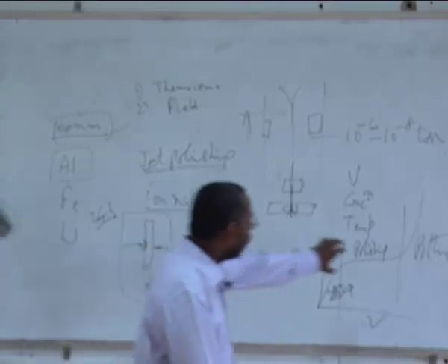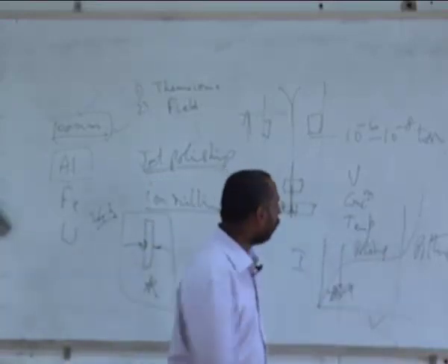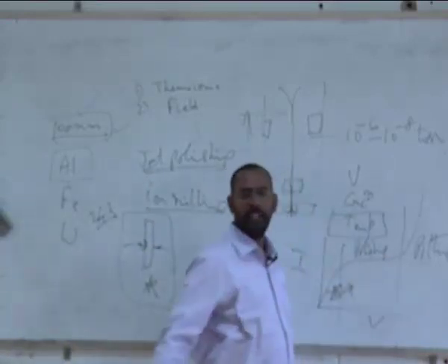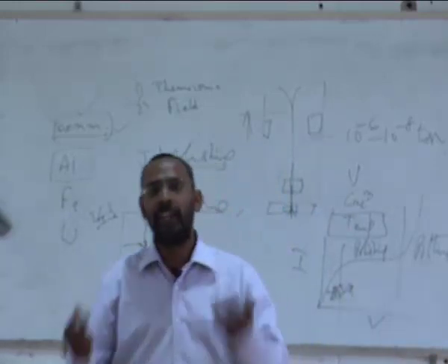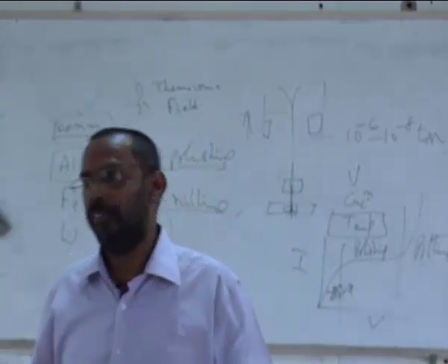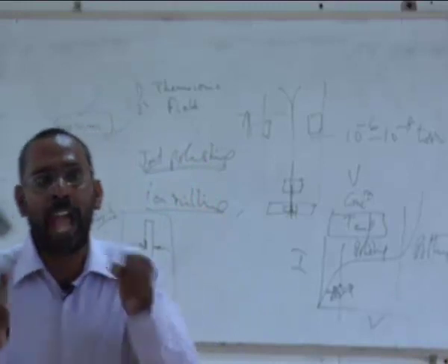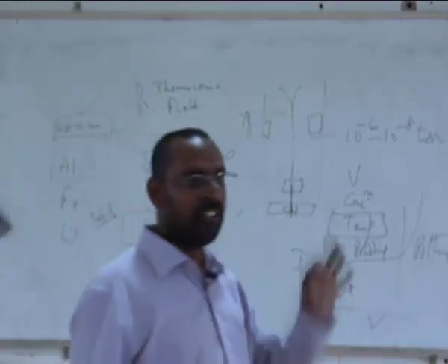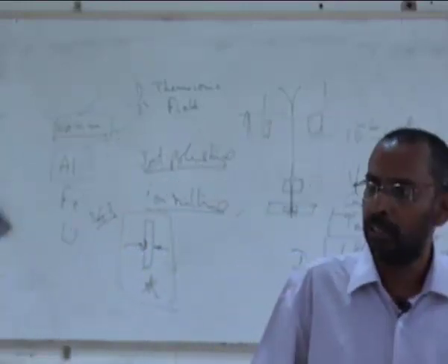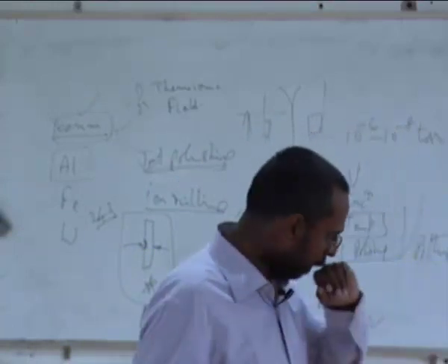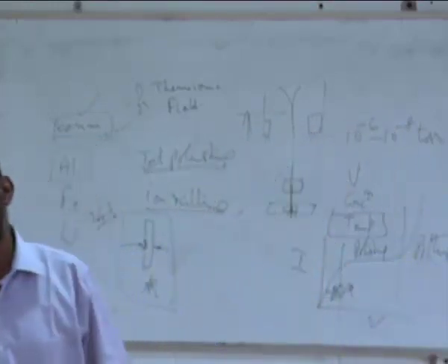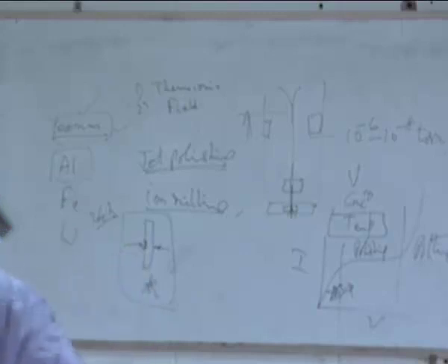So this domain has to be identified. And also, if the temperature is higher, then the material has a tendency to dissolve very fast. As a result, you are not able to catch that particular instant where just a hole has formed. So as a result, many times we do this jet polishing at temperatures which are below 0 degrees.